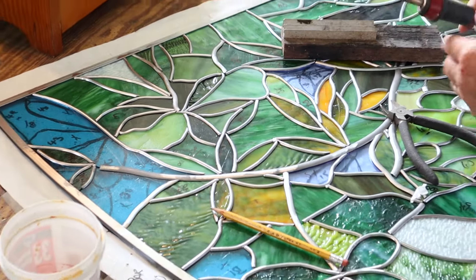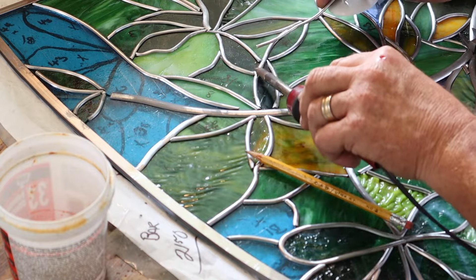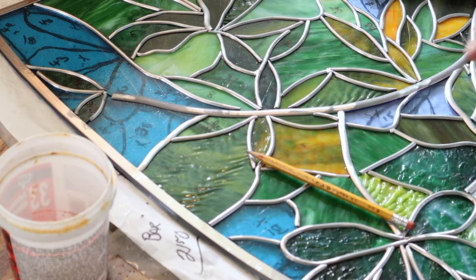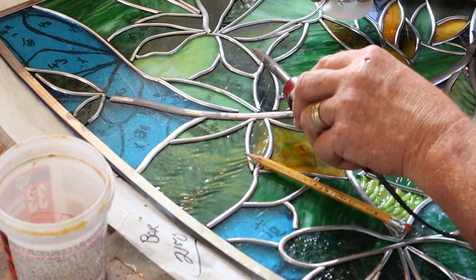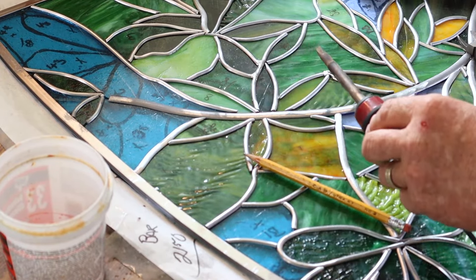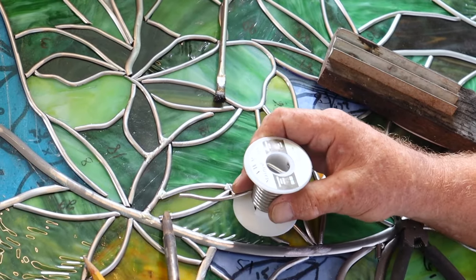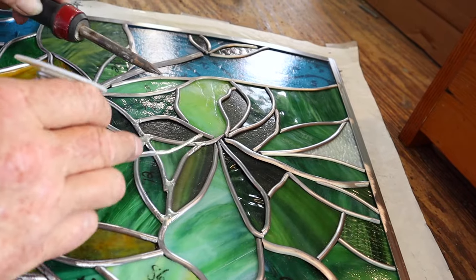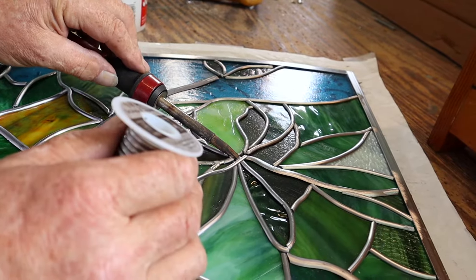We're going to take this one right here — this is a T. I've got my wattage controller and my little iron here. So my iron is a little bit hot, we're going to cool it down a little bit. I like to do what I call a touch and go. If I get the temperature right on my iron, we want to go one, two, straight up. You want that solder joint to look like a V because that's what it is — touch and go, one, two.